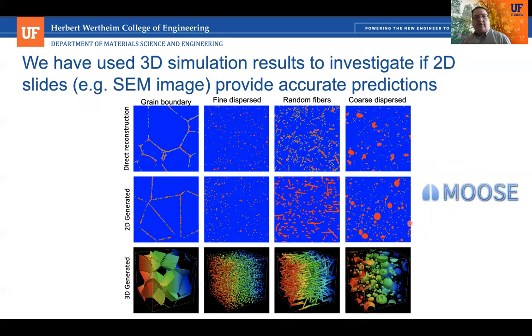Now, the next question is, well, does this approach even make sense? Well, we can take a micrograph, which is just a slice of a 3D microstructure, and just with that one 2D slice, estimate the overall thermal conductivity of the 3D microstructure. And so to check that, we actually constructed a way to generate 3D microstructures in the MOOSE code. It's a finite element code. And then we have estimated the effective thermal conductivity of these microstructures with the finite element method.